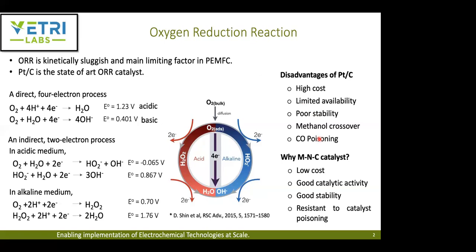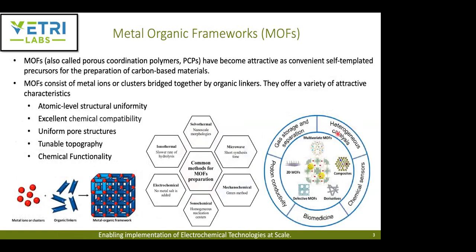One of the main alternatives people have looked at is noble-metal-free catalysts, basically MNC, a transition metal nitrogen carbon combination catalyst. The advantages are very low cost, good catalytic activity in alkaline medium, and improvement in acidic medium too. They have extremely good stability and are resistant to methanol crossover and carbon monoxide poisoning, which is a problem with platinum-based catalysts. Using metal organic frameworks, people have started to create these MNC catalysts.